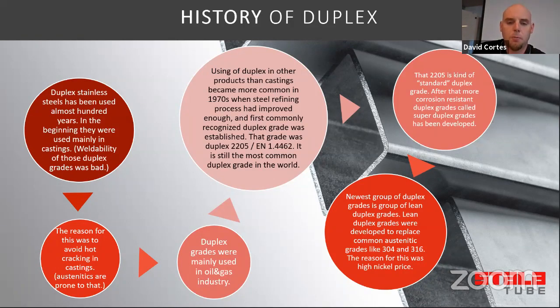That grade was duplex 2205. It is still the most common duplex grade in the world. And that 2205 is kind of the standard duplex still today. And after that, more corrosion resistant duplex grades called super duplex grades have been developed. Now the newest group of duplex grades is called Lean Duplex grades. So these were developed to replace common austenitic grades like 304 and 316. And the reason for that was the high nickel price around 2007-8, when the nickel price was sky high.